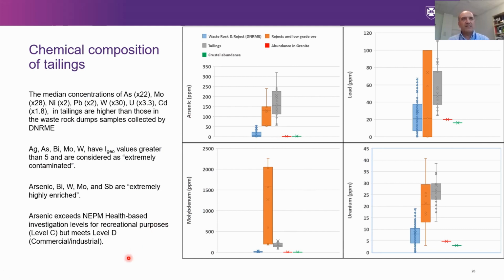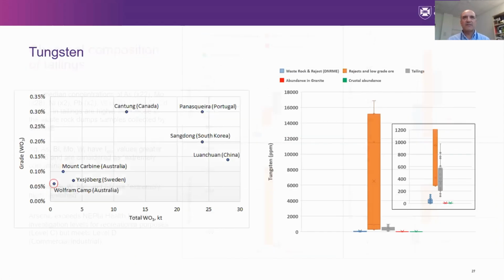But we'll talk about tungsten in a minute. You can see very high elevated concentrations of all these elements. Nevertheless, when you compare them with NEPM guidelines, it was arsenic that was above the threshold for health investigation. But I have to say that there is really no guideline for tungsten, and for a number of these critical elements we don't really have a good understanding of their mobility and toxicity, and also there is no guideline for some of these critical elements.